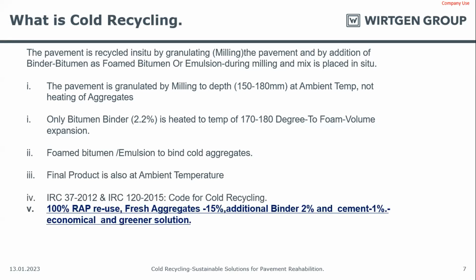The codes for the recycling of pavements are IRC 37, 2012 and 2015, as well as IRC 120. In in situ recycling, 100% RAP is used back in the system. We add 10 to 15% fresh aggregate as per the missing gradation, and 1% cement as filler. When we check the modulus in the lab, we get close to 1400 MPa, but the code specifies a modulus of 800 MPa for the recycled mixes.